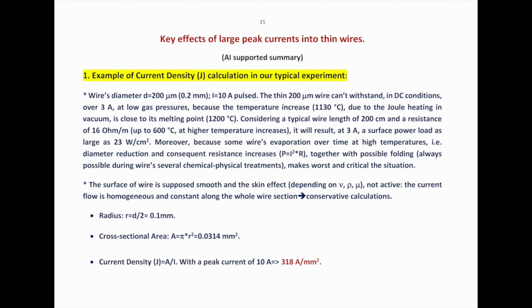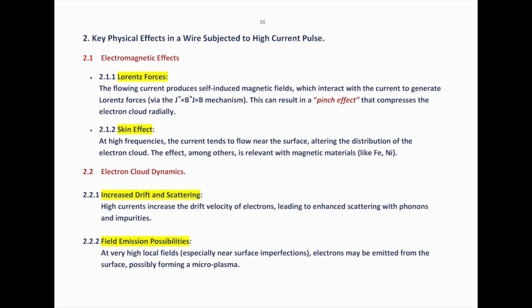Now a short summary about the artificial intelligence. Our wire is 200 micron, cross area 0.034 square millimeter, and typically we give a current between 5 and 10 ampere. So in the case of 10 ampere, neglecting skin effect, we have about 318 ampere per square millimeter. So the artificial intelligence replay.